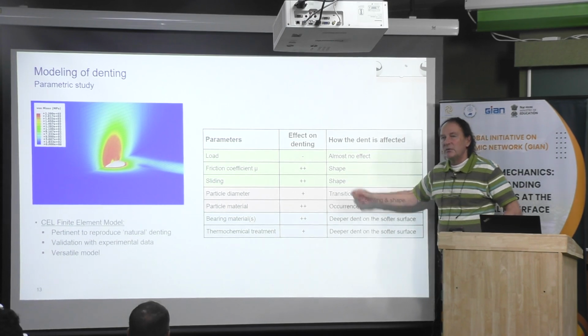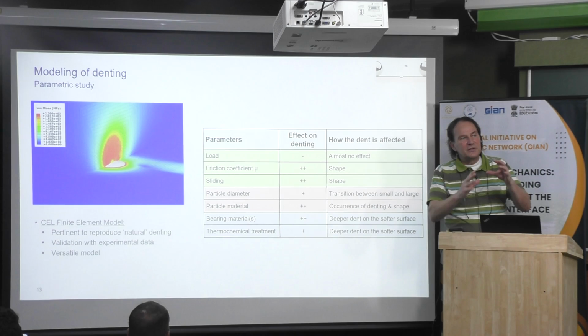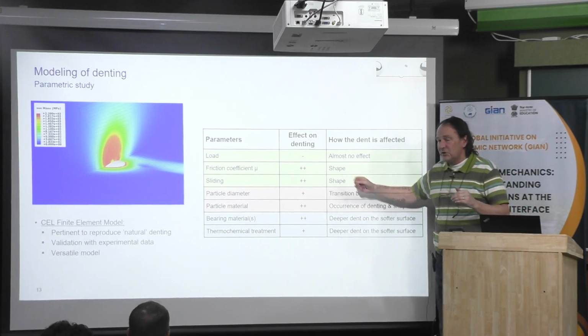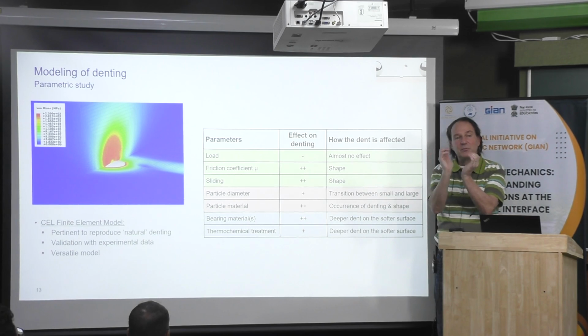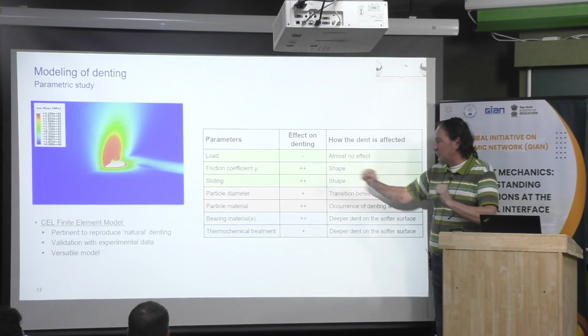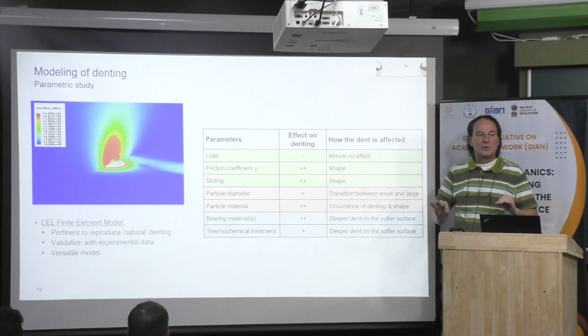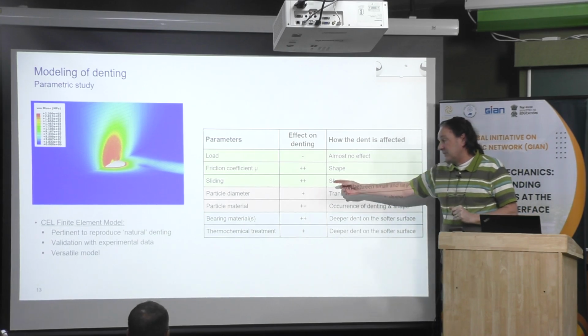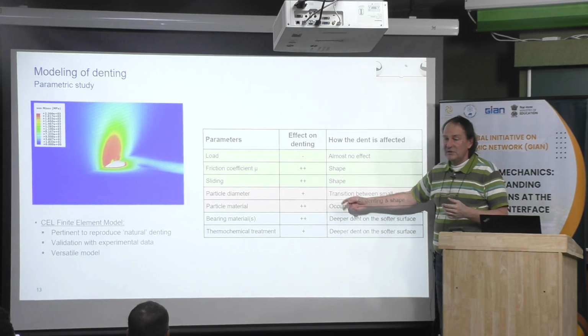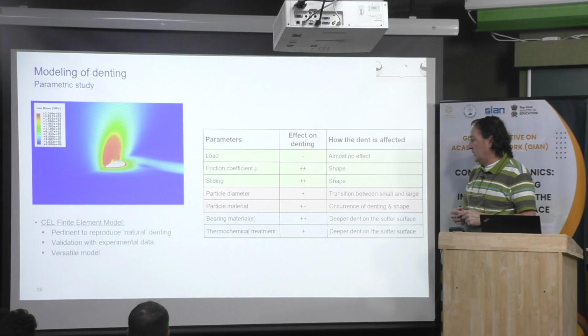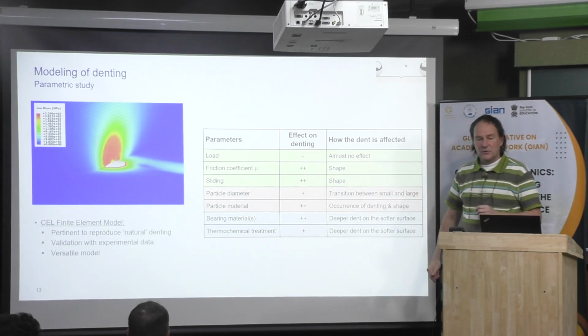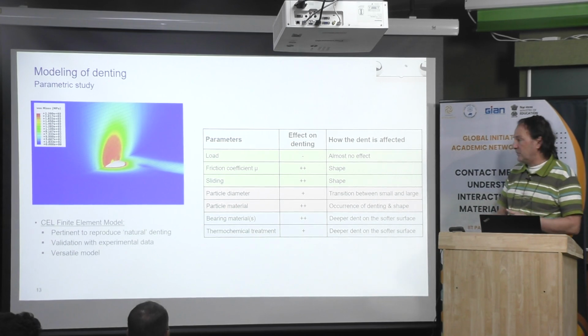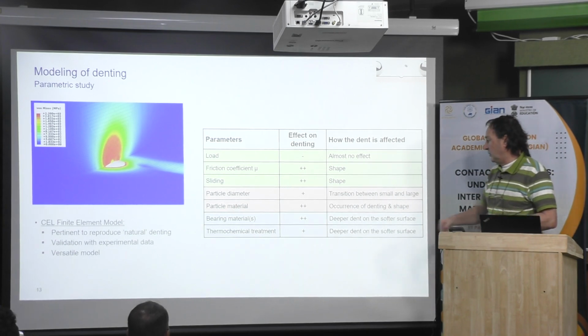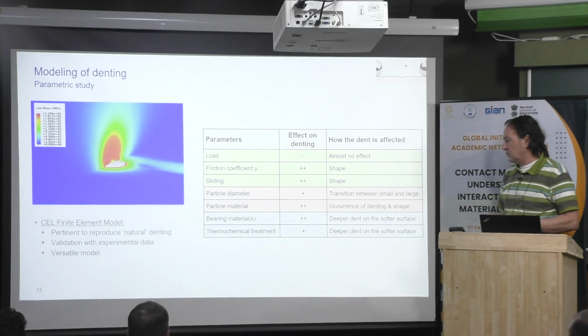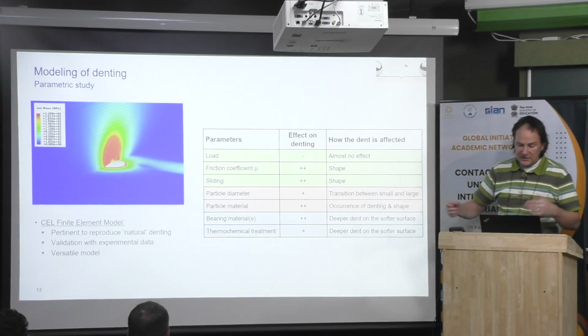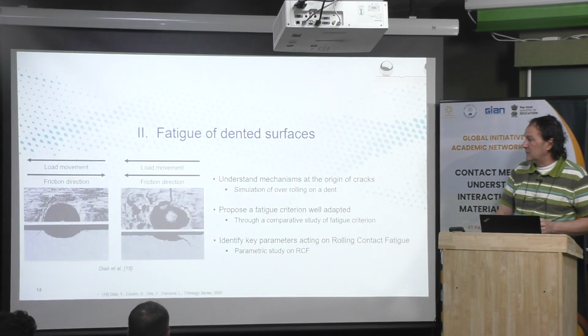In fact, the friction coefficient plays also another role, which is when the particle is deformed. When you have a high friction coefficient, it is blocked. It cannot deform a lot. It will be blocked. Okay. If there is no friction, it will easily flow between the two surfaces. The particle diameter has a very little effect, only when it is very big compared to very small. Of course, the particle material has some effect because it will affect the shape of the dent, the depth of the dent. The bearing material also plays some role, and also residual stresses due to thermochemical treatment.